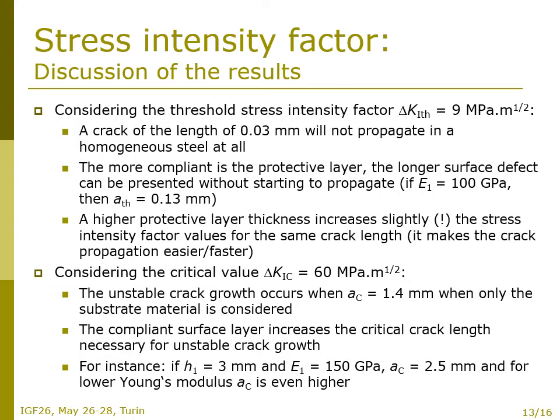Thus, considering the threshold stress intensity factor of 9 megapascal square root meters, a crack of the length of 0.03 millimeters will not propagate in a homogeneous steel at all. The more compliant is the protective layer, the longer some surface defect can be presented without starting to propagate. For example, if the Young's modulus of the layer is 100 gigapascals, then the threshold crack length is equal to 0.13 millimeters. Moreover, a higher protective layer thickness increases slightly the stress intensity factor values for the same crack length. It means that it makes the crack propagation easier or faster, let's say.